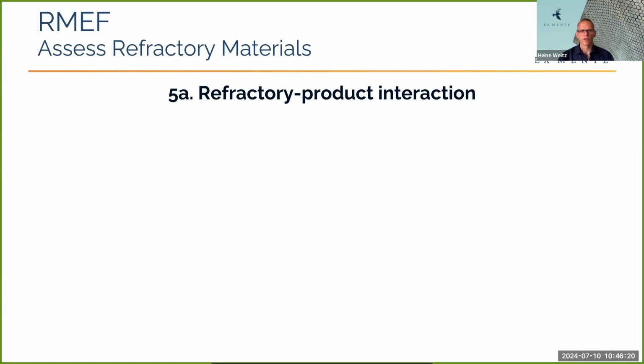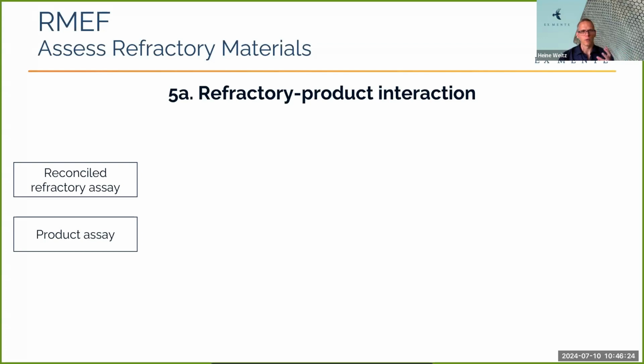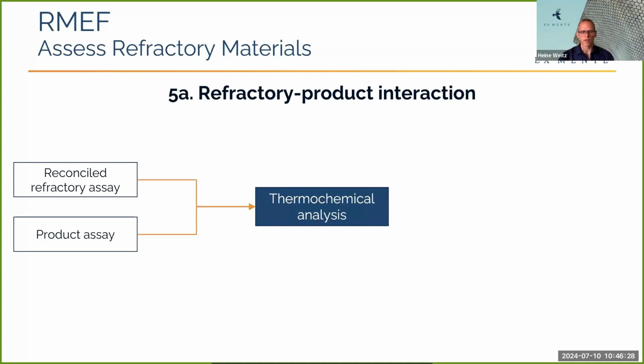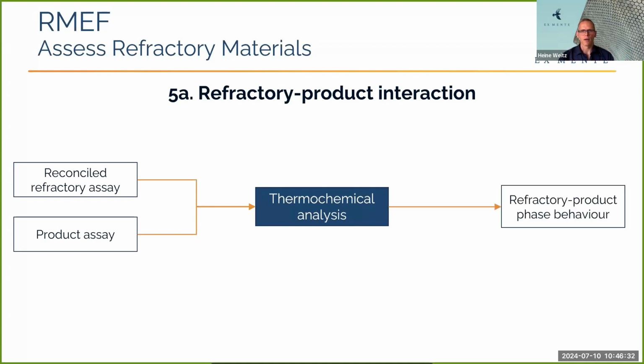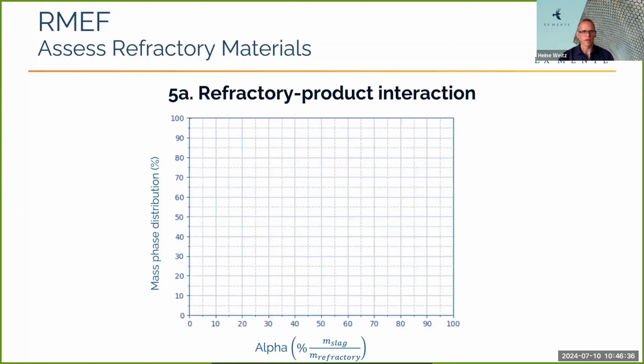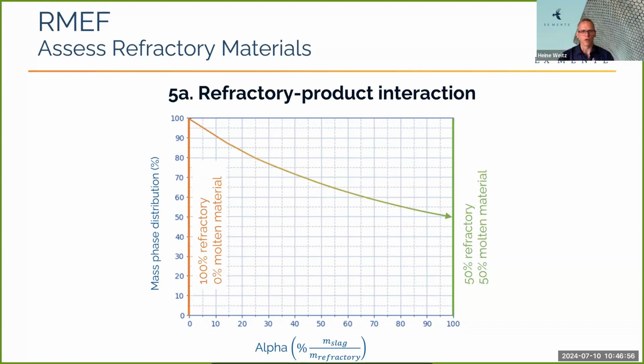Okay, then if we look at refractory product interaction, if we've got the product materials and we know what the refractory materials look like, we can put them in contact with one another, and with thermochemistry calculations, we can look at how they are expected to interact with one another. Now, this is not a simple matter because we're not sure how much slag would be in contact with a certain mass of refractory material. So what we tend to do is scan over a range of slag to refractory masses. And at the end of the day, on this picture, on the x-axis, we've got the mass of slag as a fraction of the refractory mass. So on the far right, we've got equal amounts of refractory material in contact with a slag, for instance. So we need the refractory material to remain above that line that we indicate on this graph.